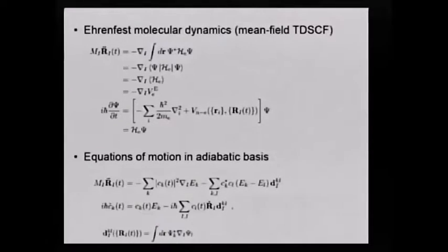But when you do this, you do it as a mean field approach. So what happens is that even if you are able to simulate other electronic surfaces to predict transitions between different PES, in this case your solution is going to be expressed as a linear combination of these states. This causes a lot of problems, especially in the systems I'm interested in, which are essentially two. One of them is more critical than the other, which are charge transfer systems, where, for example, when you are going to treat polaron charge transport, you have a coupling between the nuclear part and the electronic part in transport. You have a deformation of the lattice when you have the charge.